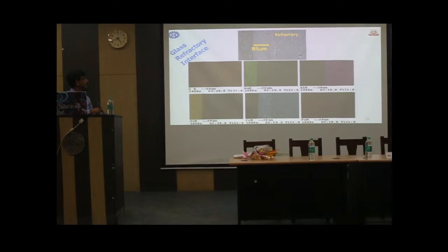You see that this is actually the interface. This portion is the glass, this is the refractory, and you see that particularly in this region the texture is different. It looks like the porosity is more. But if you see the elemental mapping, this one is the alumina chrome, and this one is the aluminum. The aluminum concentration is less in this region. That means the aluminum ion is migrating from the refractory to the glass.